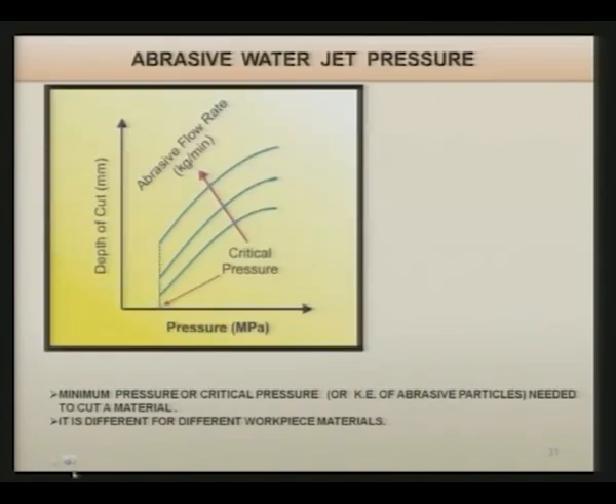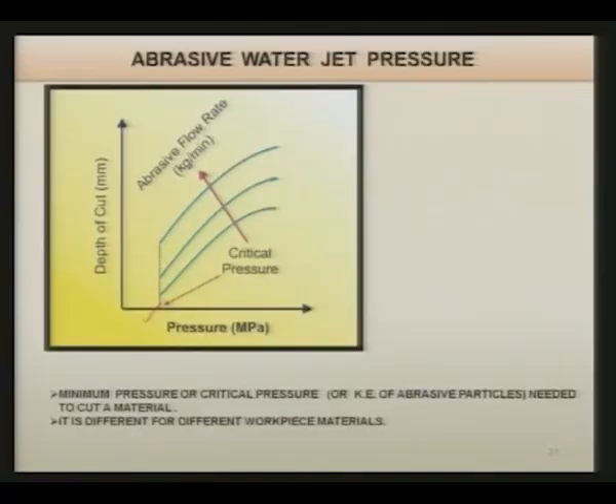Now, let us see the effect of pressure on the depth of cut. As you can see in this particular figure, there is a point which is written as critical pressure. This is the minimum pressure or minimum kinetic energy needed. The workpiece has a certain strength, and unless the kinetic energy of the abrasive particle crosses that, it cannot penetrate inside the workpiece surface. That is why you can see there is no cutting in this zone, before the critical pressure is reached. As the pressure increases, the depth of cut also increases, but this is not a linear relationship, it is a non-linear relationship, and it tries to stabilize beyond a certain